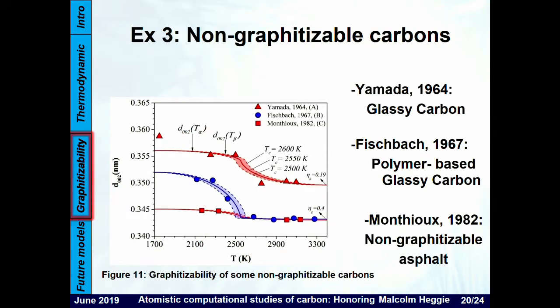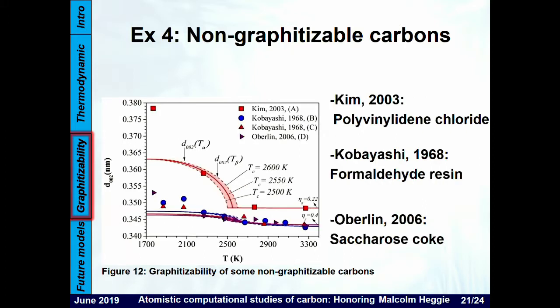Also, what is very interesting is that if you take non-graphitizable carbon and apply the same model, you get more or less sensible predictions of where graphitizability will stop, the limit for a given carbon material. Here you can see for graphitizable carbon that there is some disagreement in this region between the model and the calculation, but this is to be expected because usually in a typical carbon material, the pure carbon state is only reached at about this temperature.